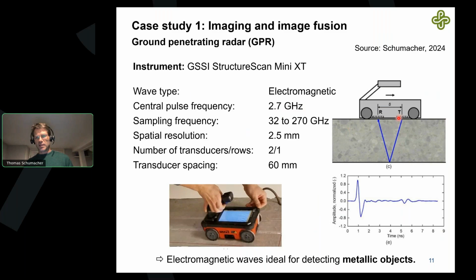The principle is shown here. So you have 2 antennas. One sends a pulse into the structure, and then if you have something inside that reflects it, that comes back, and that can be received by the second antenna. Down here is a typical signal that is generated. We call it an A scan. And you can actually see the reflection from the bottom of the thickness, in this case right here, this little pulse reflector. It takes a measurement every 2.5 millimeters as you roll this thing across the surface.